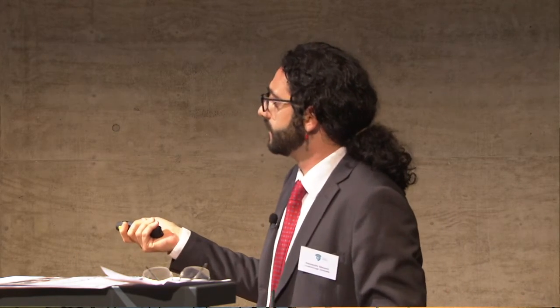So the approach we are going to use is based on 3 different methodologies. The first one is focused on the deposition techniques. We are going to use pulsed DC magnetron sputtering that my colleague will illustrate very clearly later on. The laser annealing for the activation of the device, and this is the extremely novel methodology. And then we can also draw some energy considerations about the cell for the evaluation.